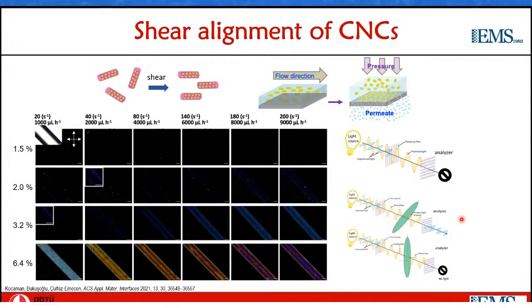So what we did is we flowed these cellulose nanocrystal suspensions inside a glass capillary, and during the flow, we observed them under cross polarizers. We did this actually at 0, 45, 90, and 135 degrees. The images here are those taken at 45 degrees, where the 0 and 90 degrees were all dark, so trying to see the highest light transmission when it occurs and whether it occurs. We did this at increasing shear rates and increasing concentrations of the CNC in the sol. So at the lowest concentration of 1.5%, in any of the shear rates, we see no alignment in the flow direction. When we increase the concentration, we start seeing some alignment, which increases with increasing shear rate. And at a certain shear rate, the alignment again increases with increasing concentration. Also, the color shift that you see from white to yellowish, reddish to whitish is also an indication of an increasing extent of alignment.